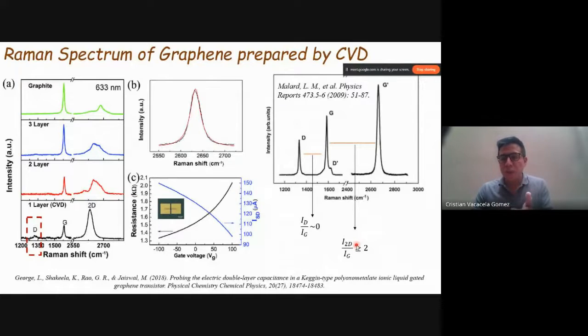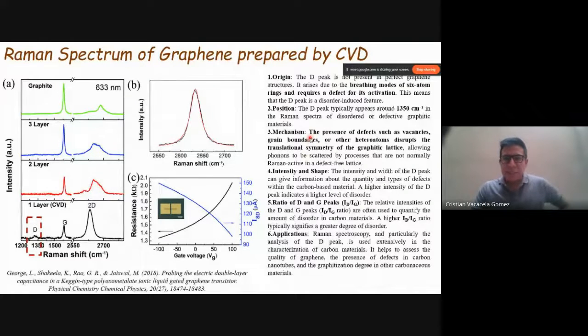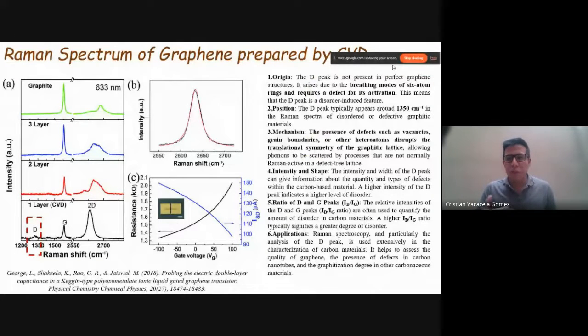So this is a very simple qualitative technique to identify your material, the number of layers, and whether it is high quality or low quality. Let me go back to this part. Now, maybe the question is: we know what the G peak is, we know what the 2D peak is, but what is the meaning of the D peak? The D peak, from the theoretical concept, is related to the breathing modes of six atom rings and requires a defect for its activation.